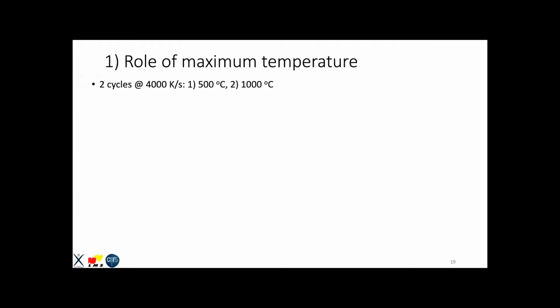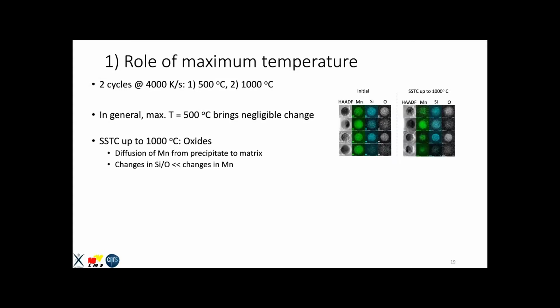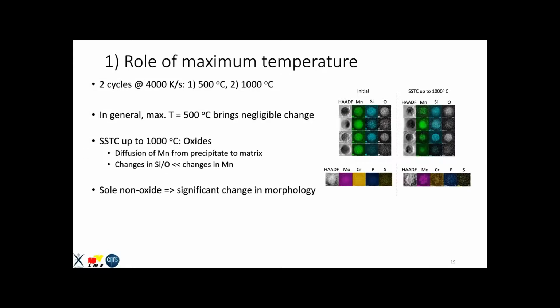We did 2 cycles at 4,000 Kelvin per second, the first one up to 500 degrees, and the second one up to 1,000 degrees. In general, the cycle up to 500 degrees Celsius brought negligible change in the microstructure in the TEM lamella, but the cycle to 1,000 degrees brought significant changes. In the case of oxides, we saw that manganese started stripping away from the oxide and diffusing into the matrix, leaving behind silicon and oxygen. There were some changes in silicon and oxygen, but not as significant as those in manganese.